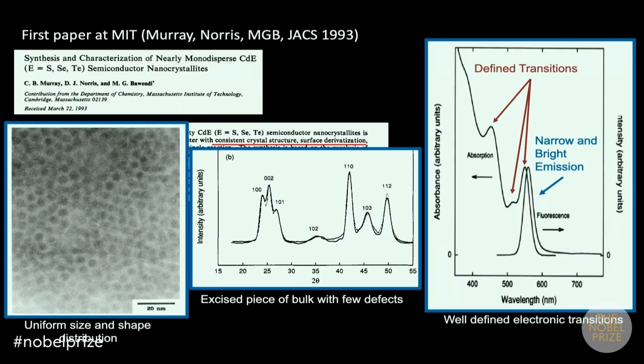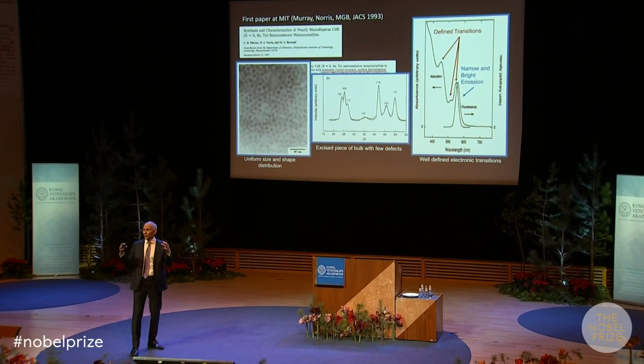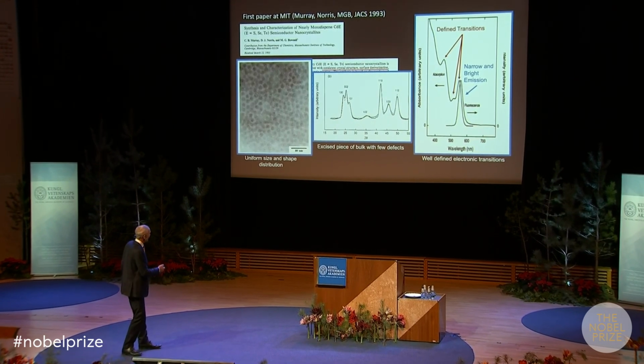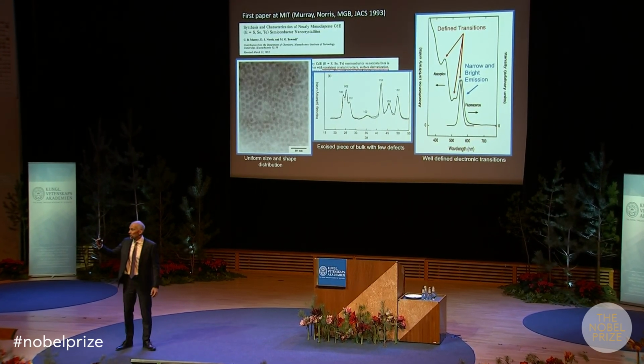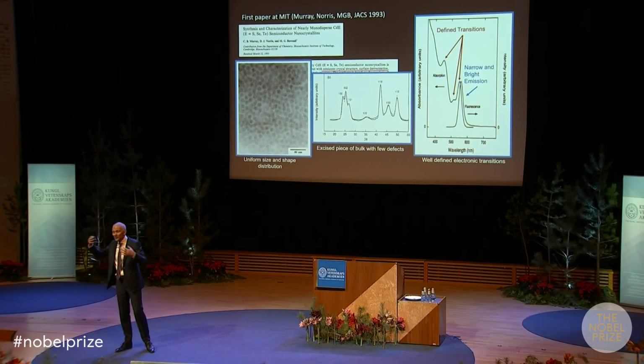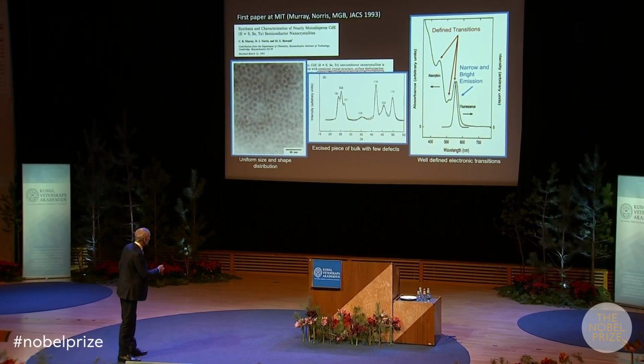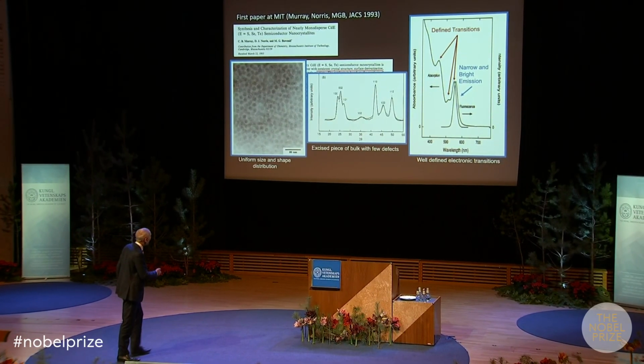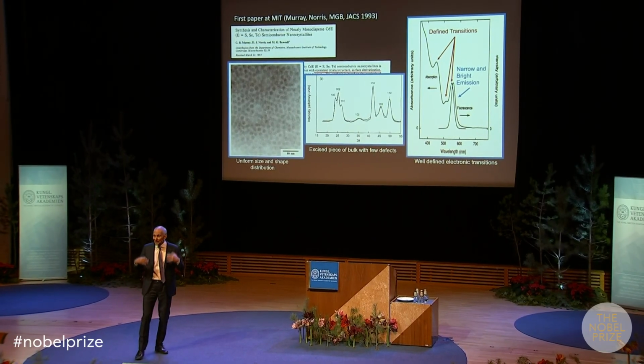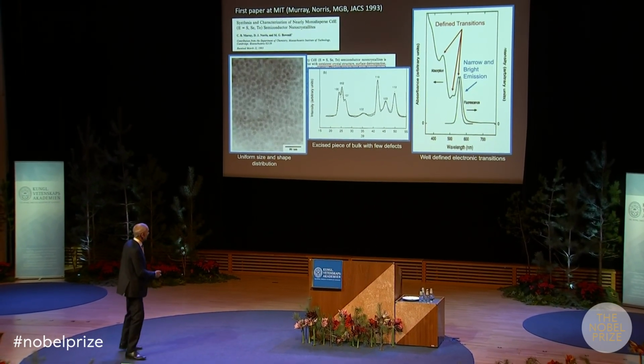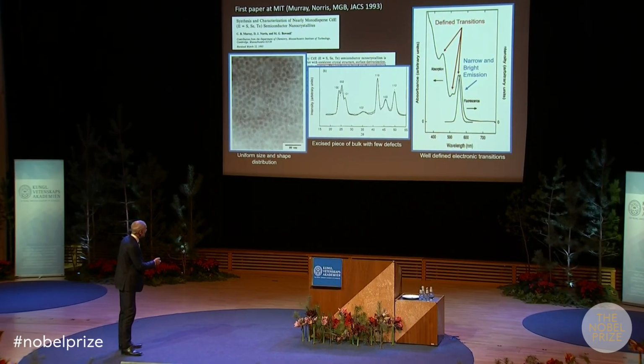And now we have this beautiful absorption spectrum. So this peak here, that was that first. This is basically the electron wave filling up the particle, and then the other peaks you can think of are harmonics. You know, like in music, you can hear the harmonics of the different scales. So these are basically harmonics of that wave here. So that was the first indication that we could see the excited harmonics of the particle, and the emission was now extremely narrow,